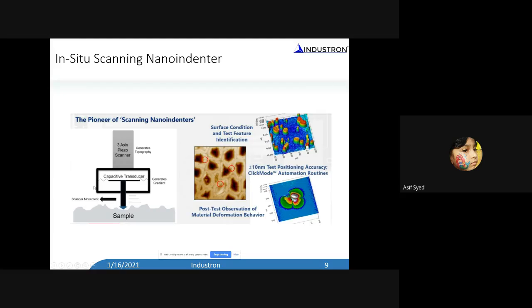So with this transducer and the scanner, we were able to scan on the surface and create this image. This image is about 20 microns, and sometimes you can create images less than a micron. So you have the ability to see what is on the surface, a kind of microscopy, which has better resolution than optical microscopy, almost closer to the scanning electron microscope. You can see the surface with high resolution. And within this image, you can see where we wanted to do this indentation experiment.